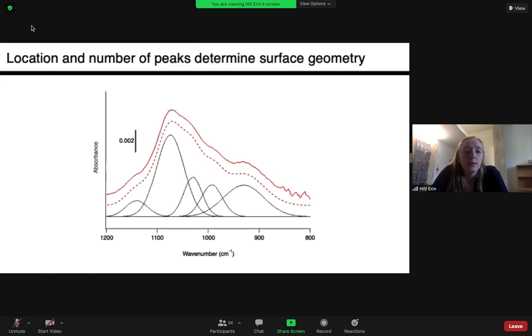So in this plot, we average those last 8 into this one red solid line. And using curve-fitting software, we deconvolute the peaks so that we could see how individual peaks contributed to the spectra. From these peaks, we determine the coordination of phosphate onto LCO.